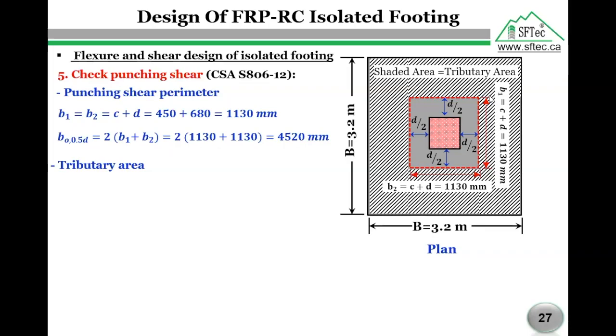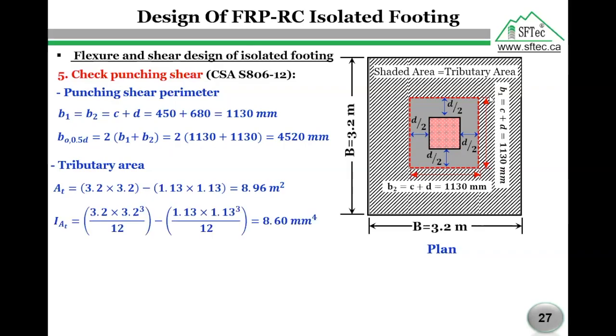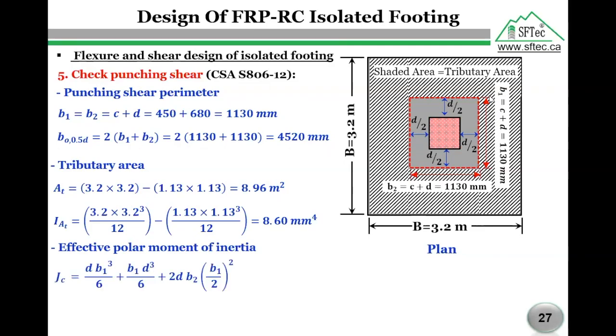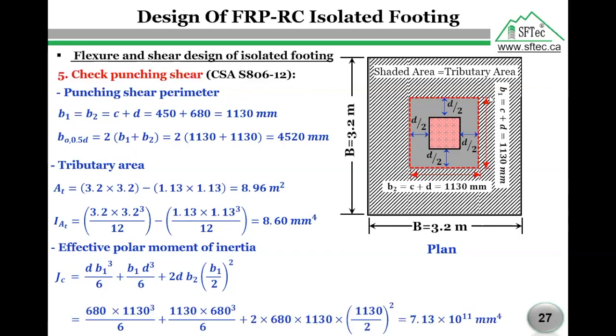How we are going to calculate it? We are going to subtract the area of the footing minus the punching shear area. So finally we have area tributary equals 8.96 meter square. Using the same criteria, we can calculate the moment of inertia for the tributary area, which will be equal 8.6 millimeter to the power of 4. The effective polar moment of inertia can be calculated using this equation, which is mainly based on the critical shear area dimension and the footing depth. So finally, the effective polar moment of inertia equals 7.13 by 10 to the power of 11 millimeter to the power of 4.